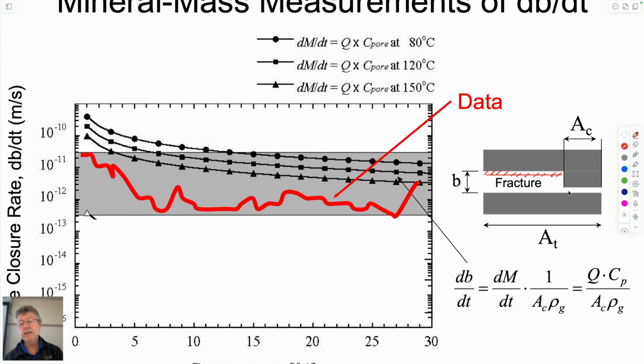So the idea of pressure solution is that if you have a fracture which would look like this, an idealized part of it, if you take the asperity contacts and isolate exactly what they are, like this, so that a portion of the fracture is in contact, this is in contact, then it turns out that if you have stress applied on this, then that has to be transmitted only across this solid component here. So the stress will build on this contact. There is no stress on this contact here.